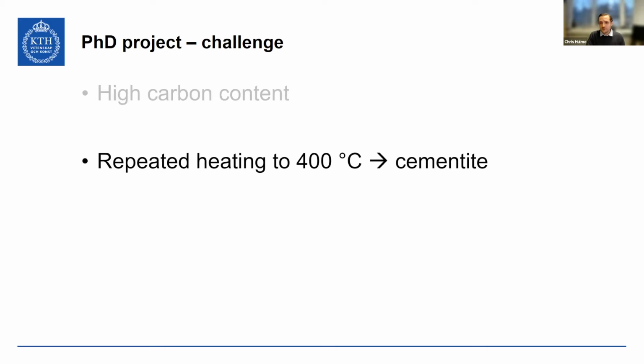But what was the main challenge? Well, of course, those of you that have worked with super bainite or read about it know that traditionally it has a relatively high carbon content. I think when I started, the base cases that I was given to work on as a starting point were about 1%, a little bit higher in carbon content. And of course, repeatedly heating it to the target temperature, which at the start of my PhD was 400 degrees. By the end of my PhD, the target temperature for the service was 450 degrees, and I was told probably it would be 500 degrees soon anyway, so you might as well just assume 500 degrees, is that you precipitate out cementite because of the high carbon content.